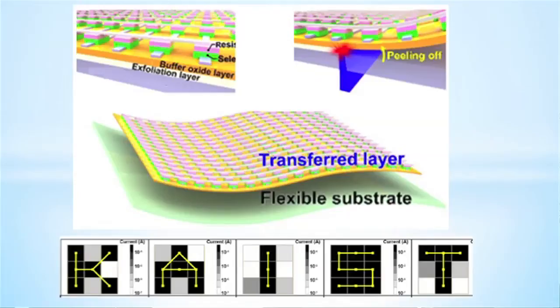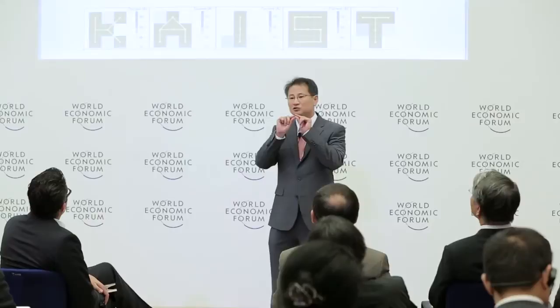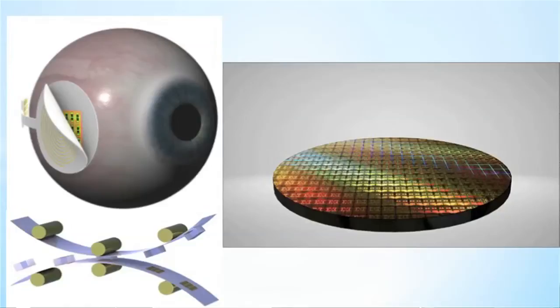The right image shows one plastic substrate with an implanted flexible OLED on the front and a flexible thin-film battery on the back, so that without any outside energy source, we can demonstrate a working display. We also demonstrate high-density plastic flexible memory devices. We fabricate high-density memristor devices on a glass substrate and irradiate laser from the backside, so we can transfer only the top 100nm high-density memory layer onto a plastic substrate.